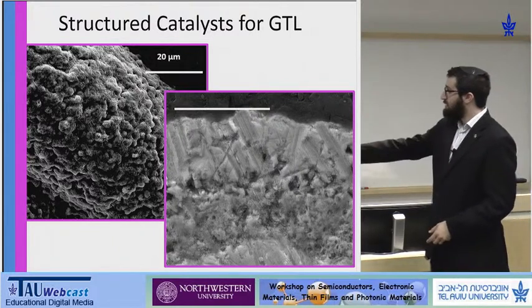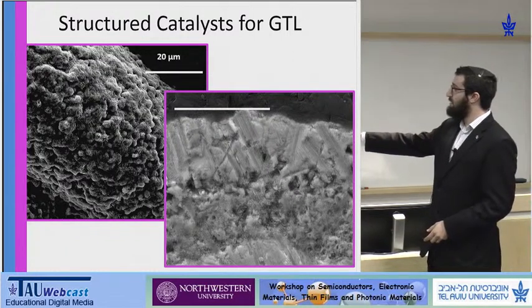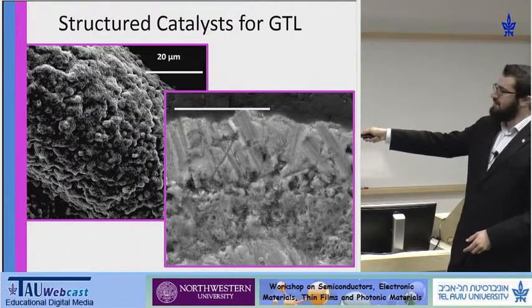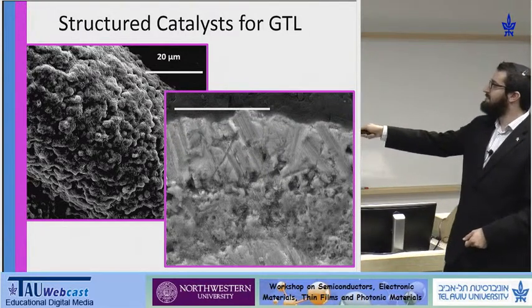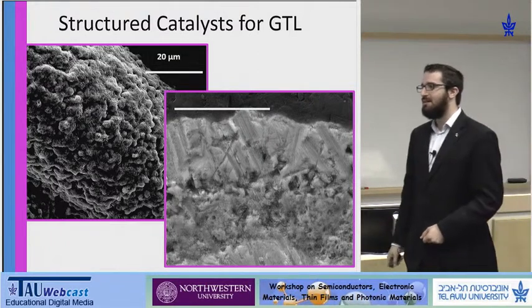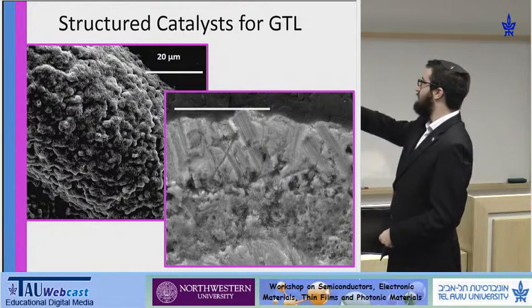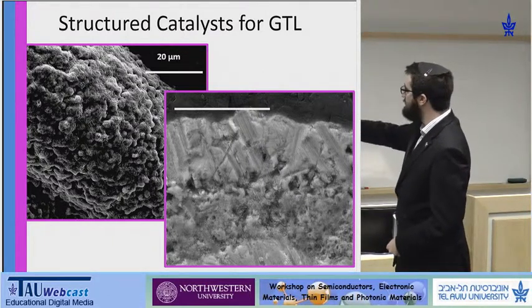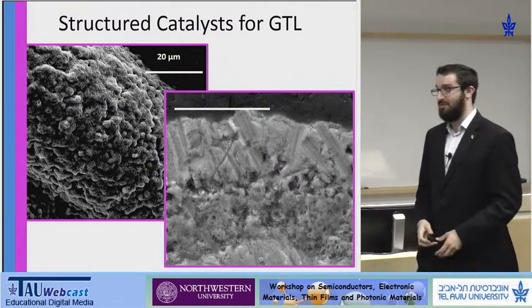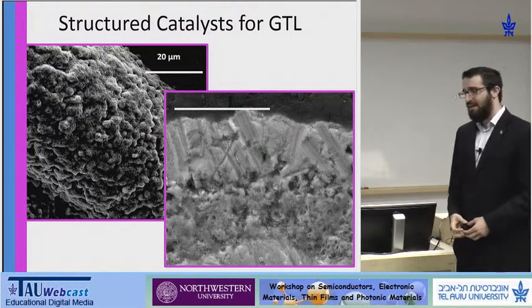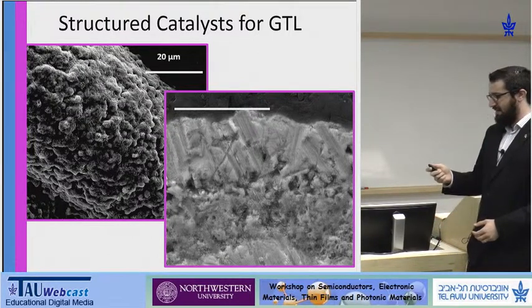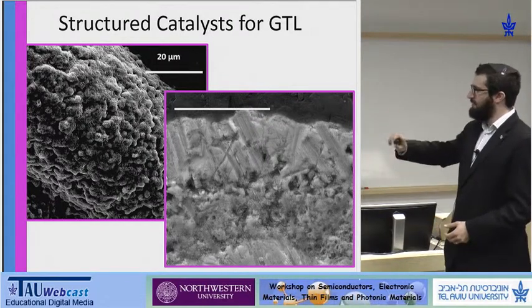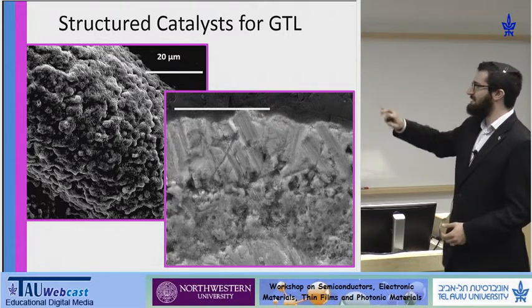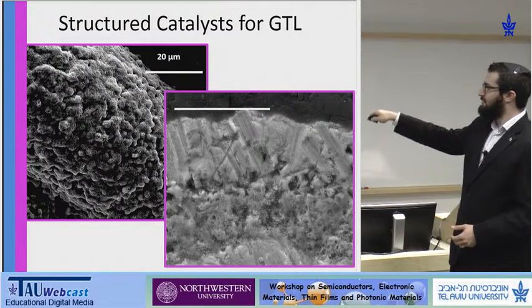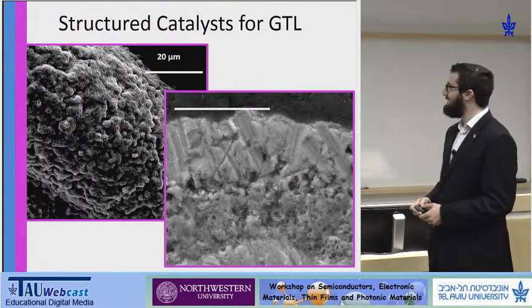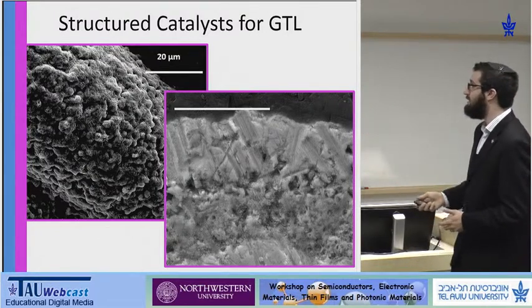And this is a cross-section of that same material. What's interesting, right here, is the interface between the stainless steel and the coating. What's interesting, and still not explained, it's work in progress, is why the porosity is much more dense in the layer adjacent to the stainless steel wire as opposed to further away. Up here is where we're seeing the porosity, but as we go down into our film, we see that there's a non-uniform distribution of pores that's dependent on depth, and this is still something that we're investigating. We're going to do various TEM and SEM studies with mapping of elemental contributions and different investigations to see what are the structural differences between these two lamellae, which could be causing this, not segregation, but the two different densities of pores.